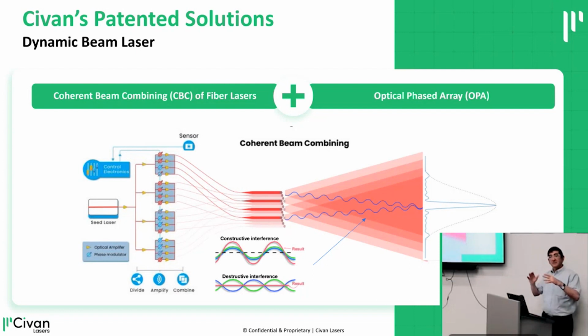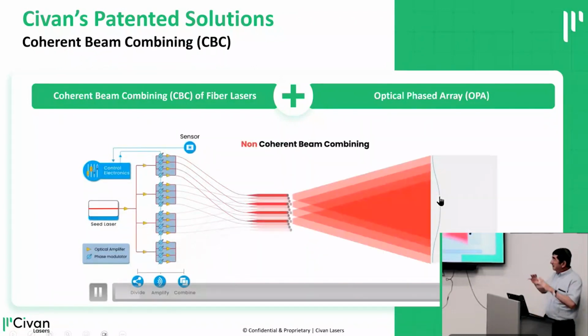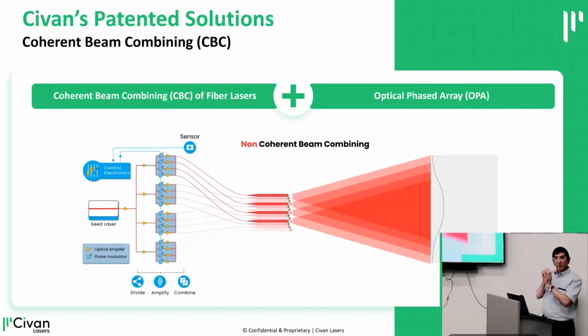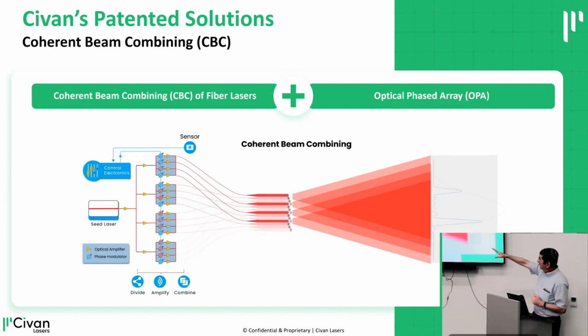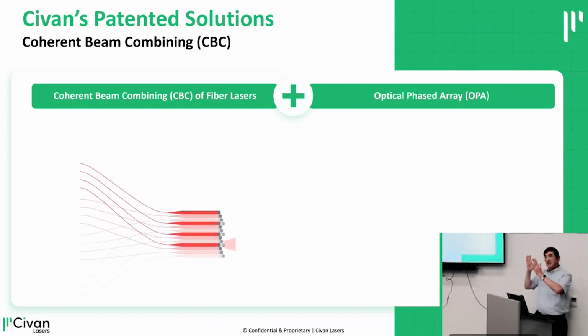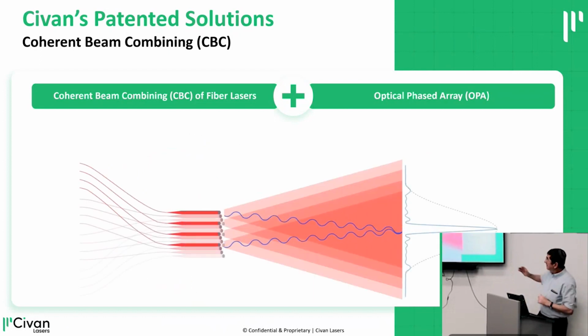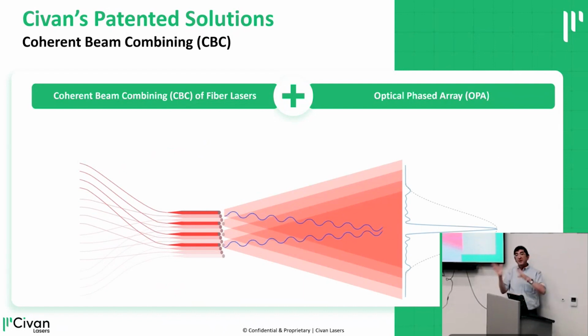So all this energy, in this example, 32 kilowatts, that was spread over 300 micron, all of a sudden is all condensed. All the 32 kilowatts is condensed to a very small spot in the center. In our case, it's about 50 microns. So instead of having a spot of 300 microns, we have a spot of 50 microns with all the energy. Okay, so this is the beginning when it's not coherent, but when it is coherent, it all condenses to a small spot. And because of the different phases, we can actually manipulate this constructive interference to happen where we want.